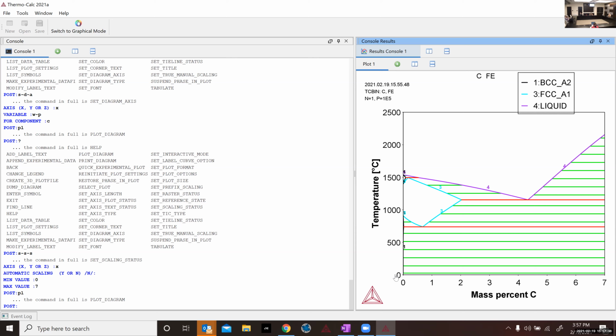Undefined. You have a 1 over T term. What's 1 over T? It goes to infinity, right? So when you get down close to 0 degrees Kelvin, all those free energy functions that they use to describe the free energies of the phases, they go to heck anyway. So I tend to use the free energy functions down to about 200 K. But free energy functions for intermetallic phases, I stay away from. I will only think about BCC, FCC, maybe HCP down to 200 K. And that's if I want to calculate things like driving force for Martensite formation.